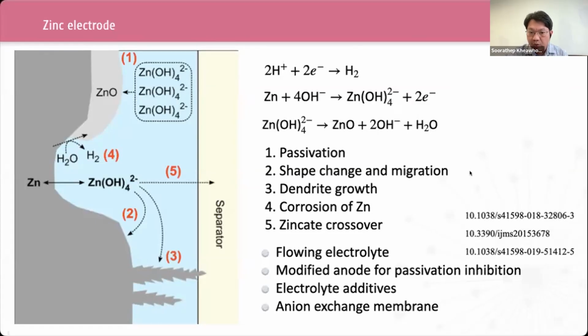And the last one, zincate crossover. The discharge product is zincate, and it can transform to zinc oxide. If zincate ions move across the cell to the air electrode and precipitate into zinc oxide at the air electrode, the zinc oxide can block the air channel and passivate the active site of the catalyst. Our group works on these issues using different strategies, such as using flowing electrolyte, developing modified anode for passivation inhibition, using electrolyte additives, and even developing an anion exchange membrane. These are some of our work addressing the issue.